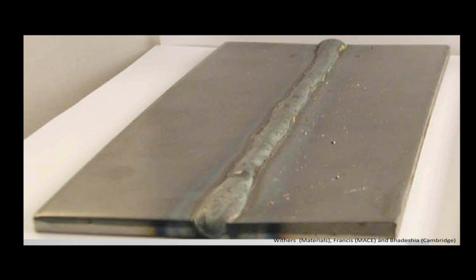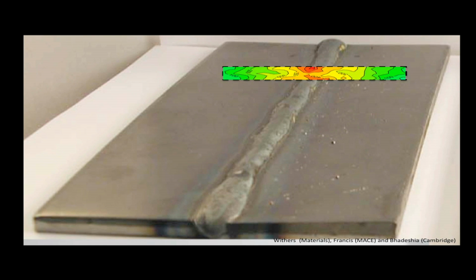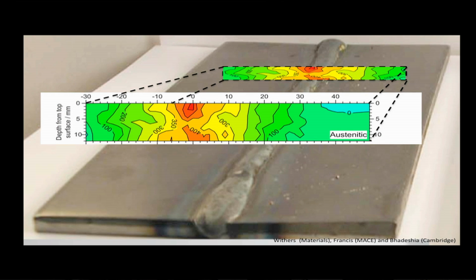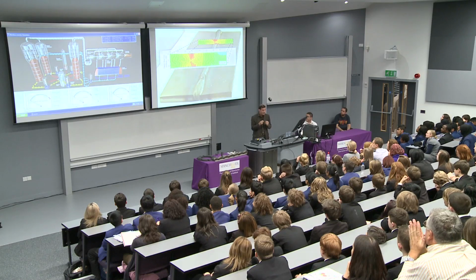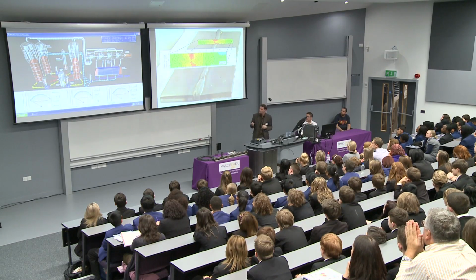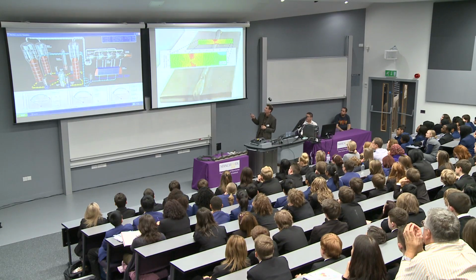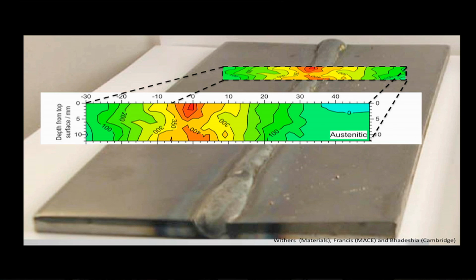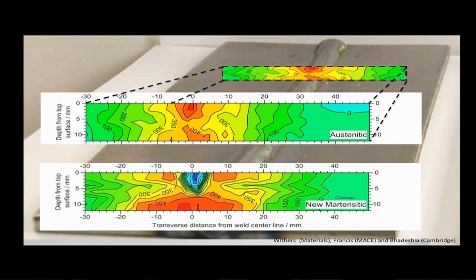So again, we're doing some research here at Manchester on trying to improve the quality of welds. So here's a weld. If we took a little section through it and we plotted the state of stress within that, you can see the sort of red hotspots, which is where you've got these very high tensile stresses. Well, what we're trying to do is to design new weld materials that actually convert that tensile stress on the surface, on the outer surface of this, into a compressive stress.